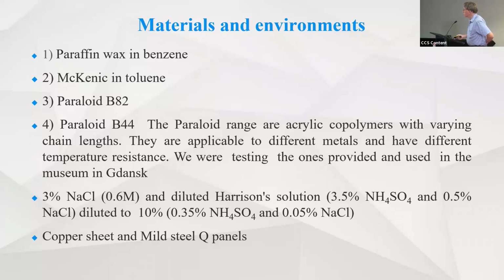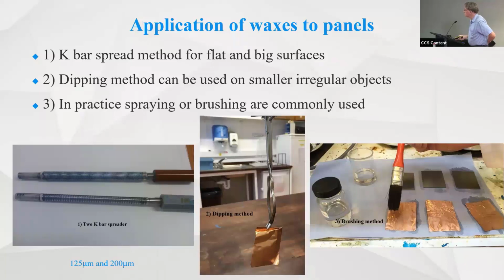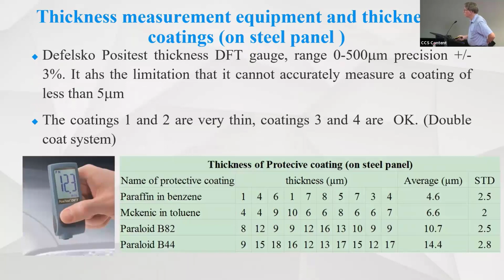So we did some simple lab tests using the normal sort of things that we might find in the lab, spraying or brushing, dipping. I think we did dipping and spreading here for these particular experiments. And we measured the thicknesses, which we're able to do in the lab, pretty thin. You can see only a few, 5 micrometers, 10 micrometers, so you're talking very thin coatings. But that's what you want with this sort of work, because you don't want the coating to be visible. It's protecting the object in the museum or outside, but not visibly.